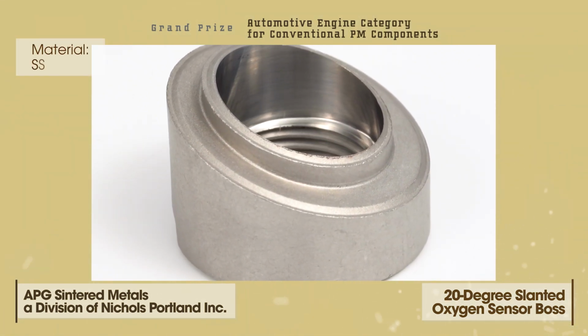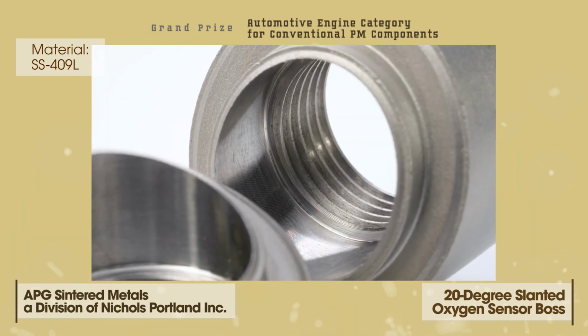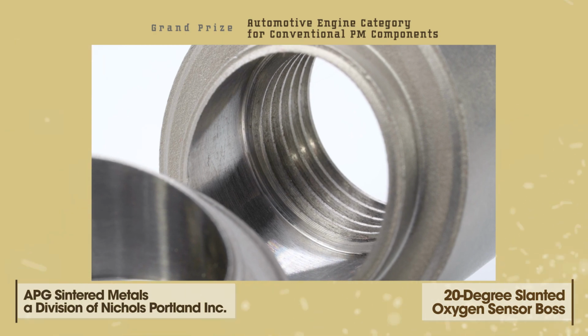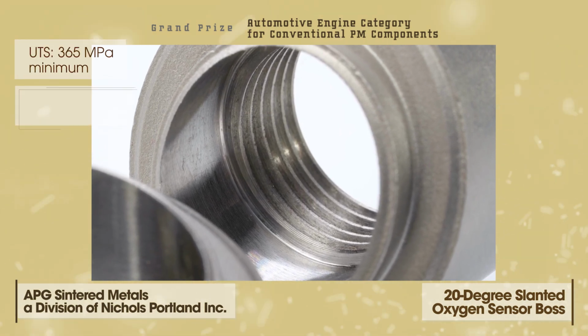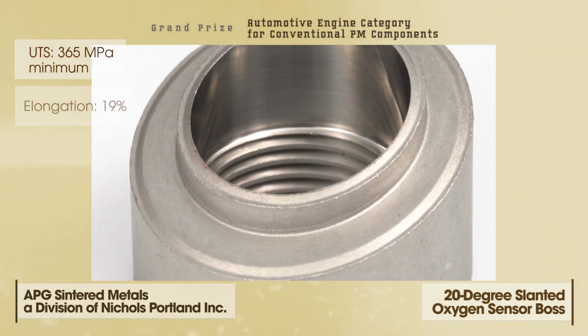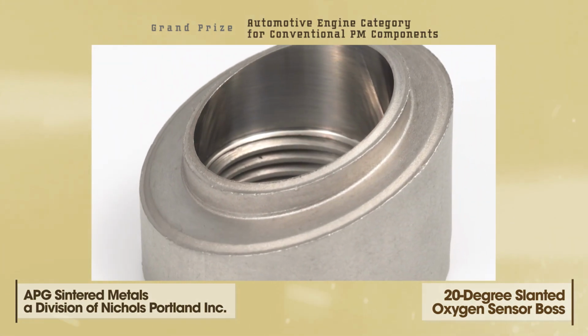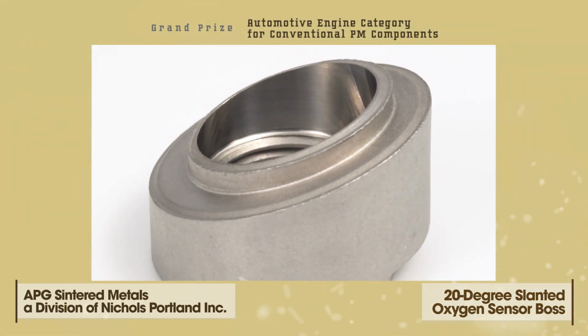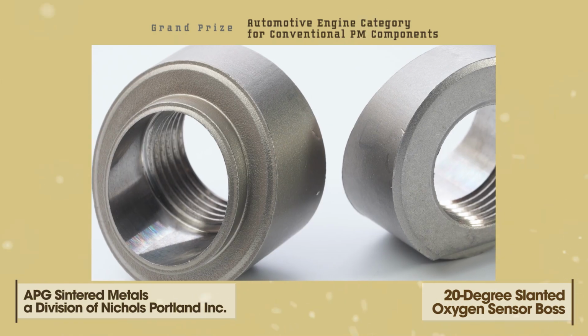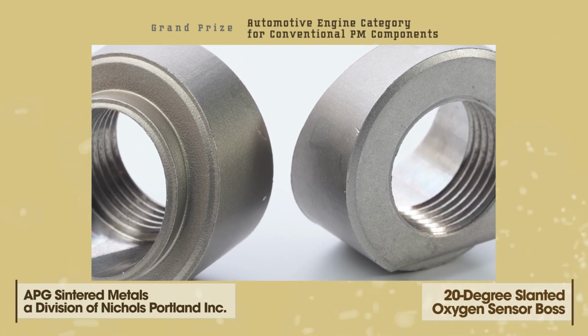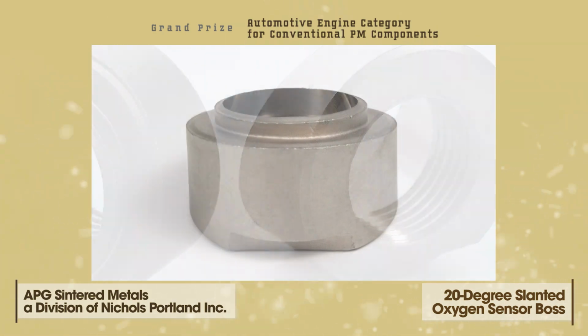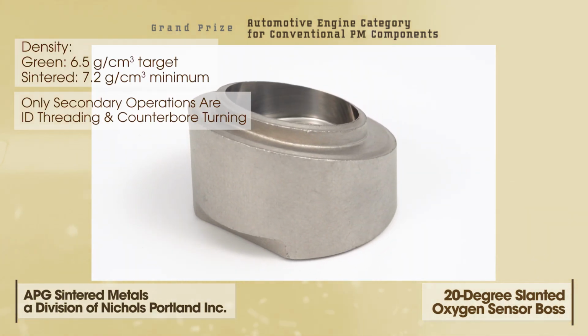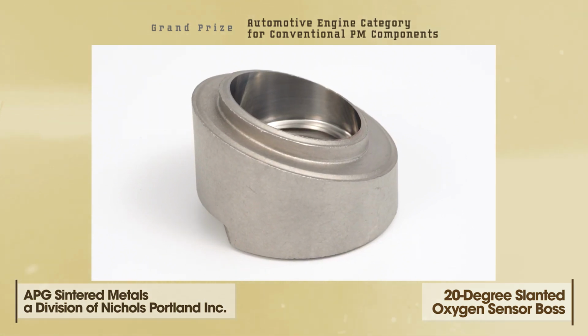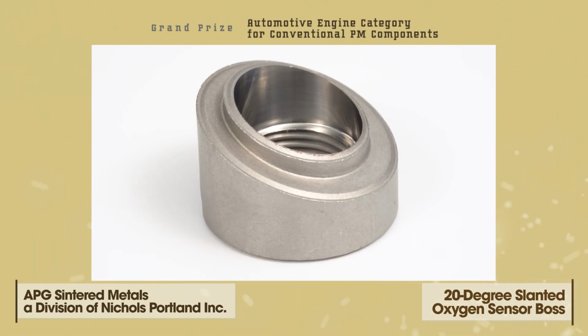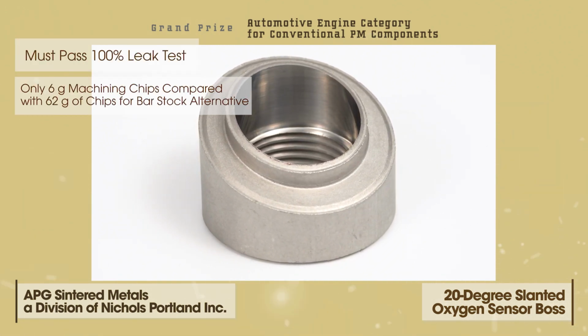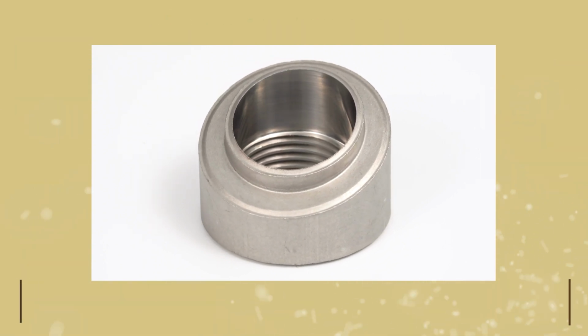The SS409L material was selected for its weldability, adequate corrosion resistance, and relative cost compared with other higher alloy content materials. The only secondary operation is threading the ID and machining the counterbore in a high-speed automated lathe. Controlling the fill depth and compaction ratio across the lopsided flange and hub requires a bolt-on angled 3D metal printed die extension and custom feed shoe. A green density of 6.55 grams per cubic centimeter is targeted and sintered to a minimum density of 7.2 grams per cubic centimeter. The sintered density prevents surface-connected, interconnected porosity between the ID and the outside surfaces and enables the parts to meet a 100% leak test at the customer's assembly facility.